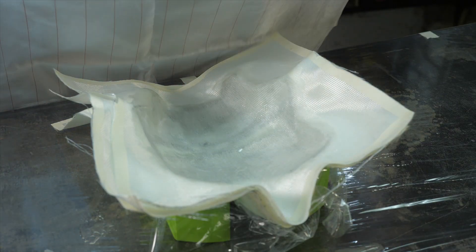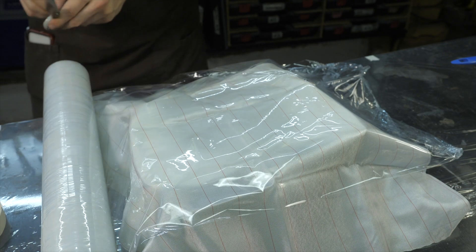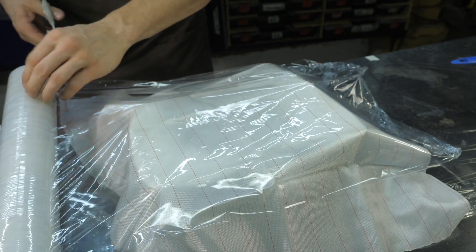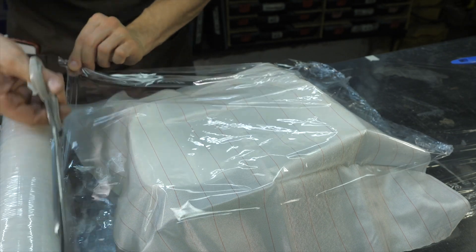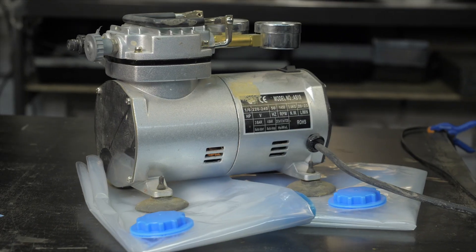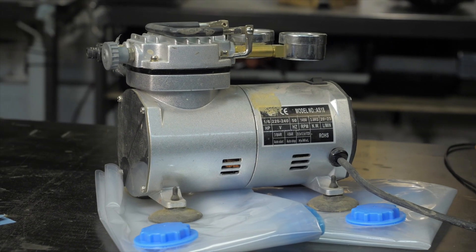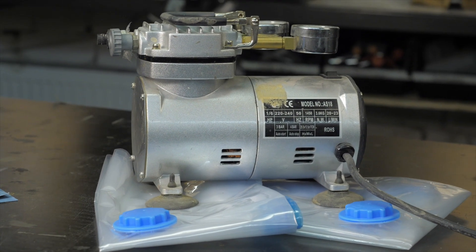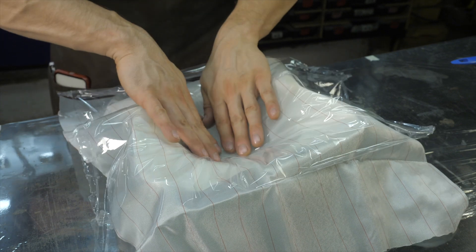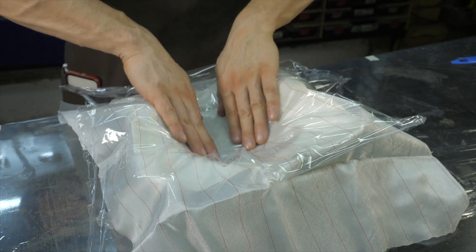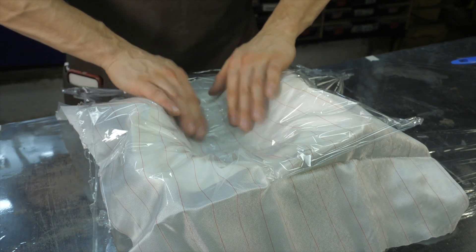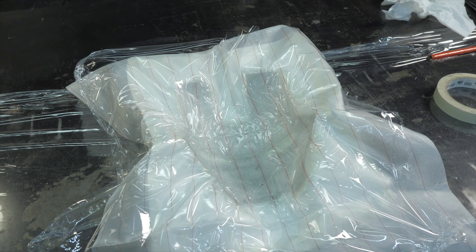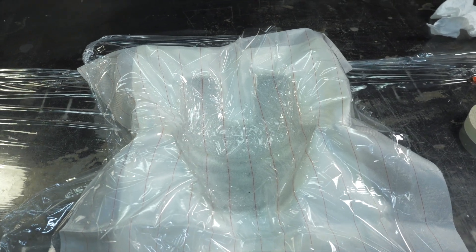To prevent resin from dripping towards the center of the concave part and get to smooth, matte inner surface, cover the part with a nylon peel ply. For denser and more durable lamination, vacuum bags can be used or cover the part with a food film and press plasticine on top, packs of water or sand to create uniform pressure over the entire area.